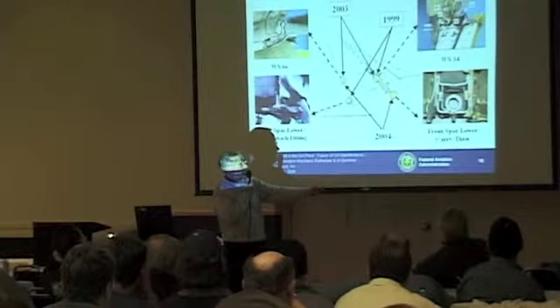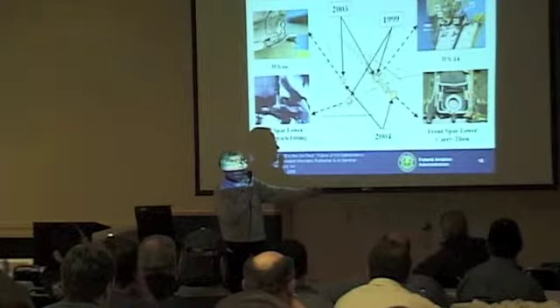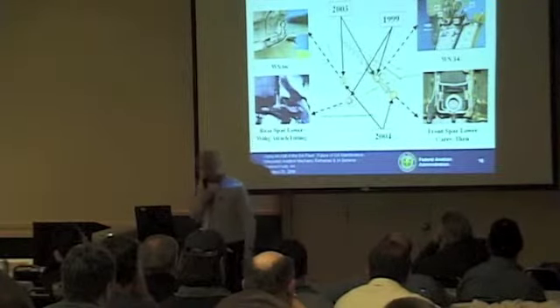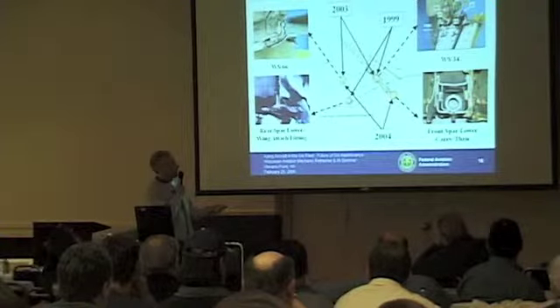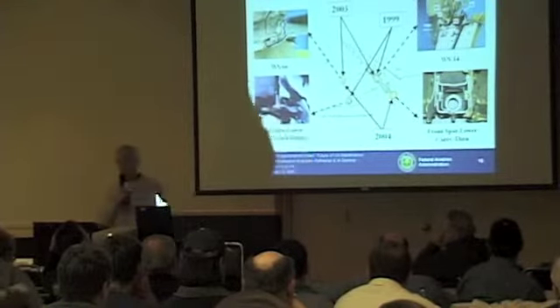Well, the outer channel is cracking too. There is no guarantee that if they don't find cracks here, that there are no cracks here. Okay? So what it amounts to is ultimately they're going to have to come up with a fix before those airplanes are going to be able to go much more. Right now, they've got an inspection here that we have given them 240 hours, because we know that we've got some crack growth capability there that even if they couldn't find cracks there, they've got enough time to go 240 hours. Not every 240 hours, 240 hours. So some of those airplanes have used their 240 hours up, and now they wonder what the next step is.